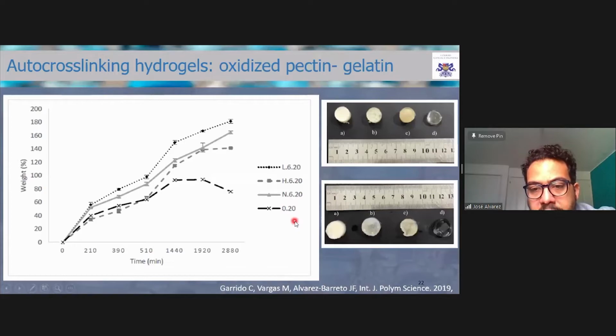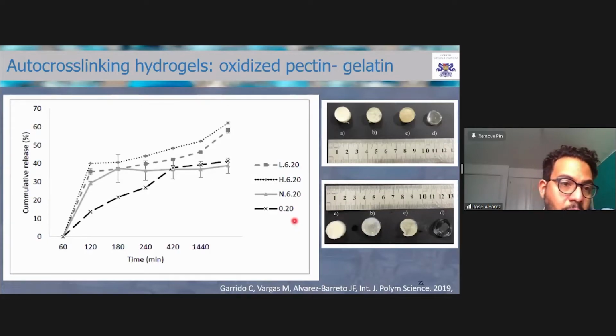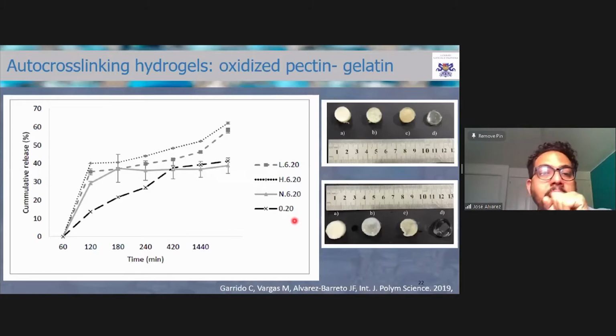And then we also looked at cumulative release. In this case, we used acetaminophen, and we also saw very interesting differences in the release profiles. So you could tune the release profiles based on how much oxidized pectin you have, and also what type of pectin you're using. I didn't put these results here, but we did this with orange pectin.